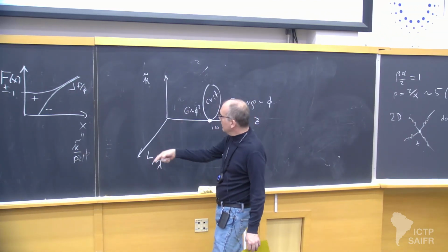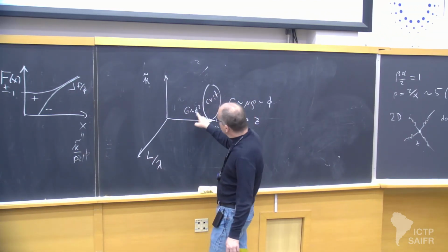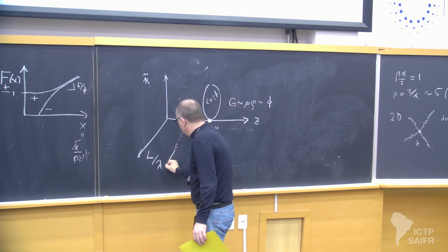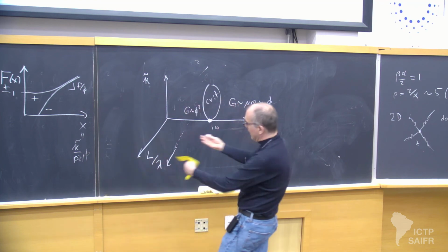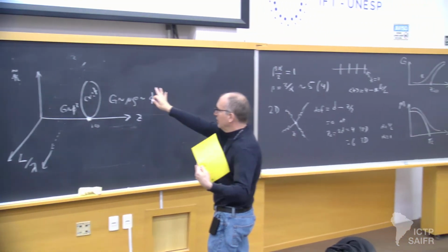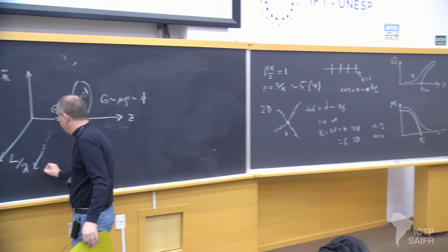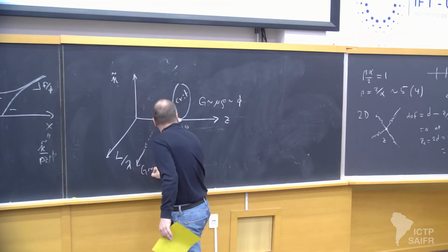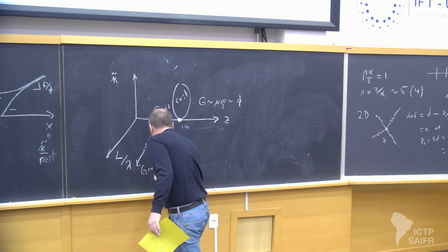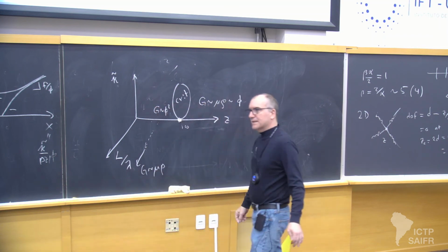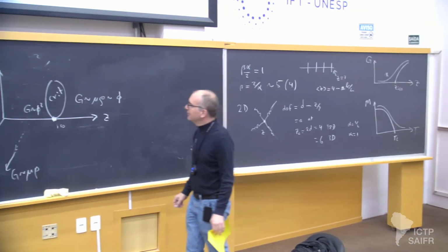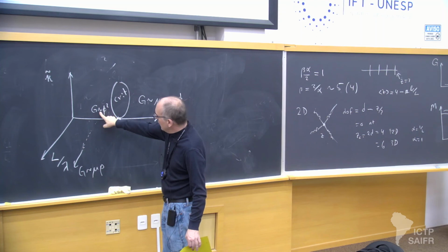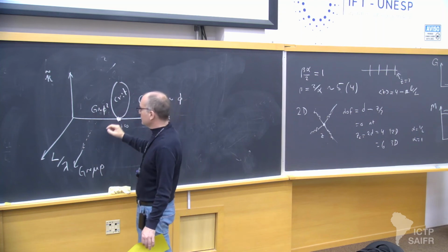I could go to high molecular weight. And even if I go out here, way down here, or way in front of this original 2D phase diagram, I would get G, again, proportional to mu rho. That's the high molecular weight affine limit. So that's what happens to this. I get a crossover from this weak modulus to a stiffer one.